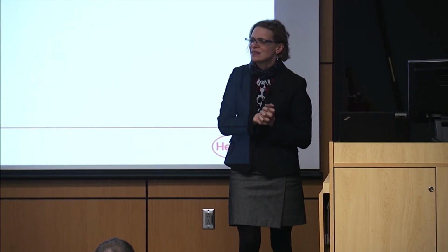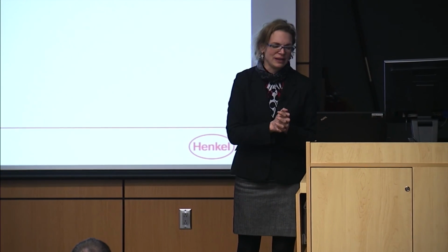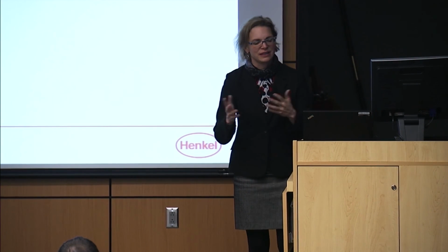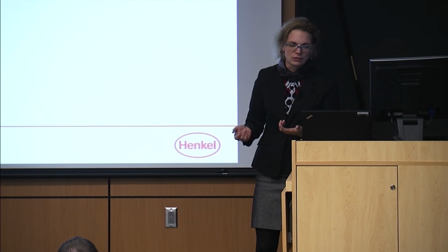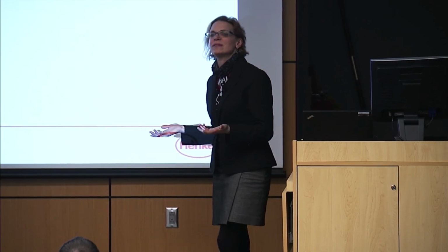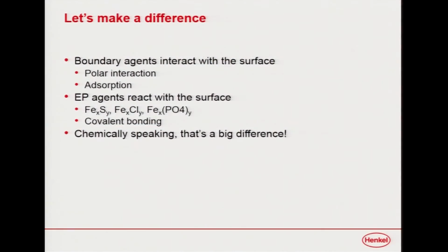So you don't experience this catastrophic damage to the two surfaces. But these materials only work when there is extreme pressure. Is the mechanism the same, was the big question. And actually, no, of course not. Because carboxylic acids, when they react with a metal surface, they form a polar interaction. They form a polar bond. They don't actually, quote, react with the surface.